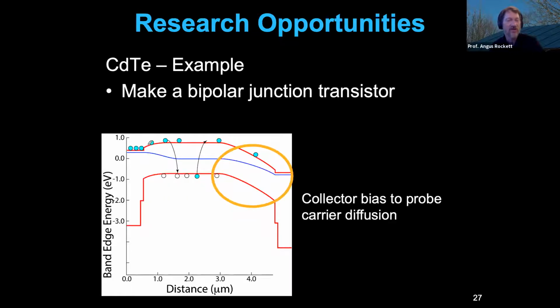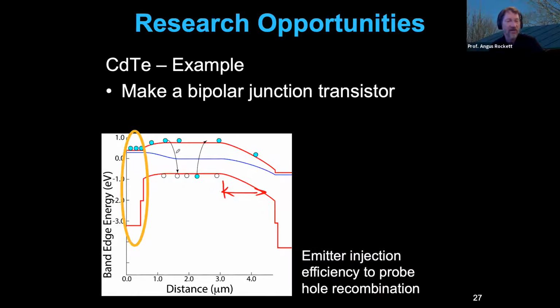We can also adjust the so-called collector bias, the reverse bias junction, and understand about carrier diffusion because we can adjust this depletion width on one side of the device, and therefore we can collect carriers from the middle differently depending on that reverse bias, and we can study that dynamically. We can also look at the so-called emitter junction and look at emitter efficiency, and that will tell us about recombination of the holes at that junction. So I think it's an interesting opportunity.